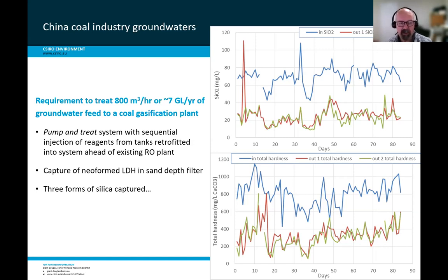This was a pump and treat system. The groundwater was pumped up out of the ground. We then retrofitted this system where we had sequential injection of the reagents. In this case, it was only 2 reagents that were injected. You'd inject one, have an in-pipe mixer, inject the second, and again have another in-pipe or static mixer. So very, very simple. Then we had the neoformed layered double hydroxide, which was captured in a sand depth filter. That was a really efficient and quick way that we could treat this water.